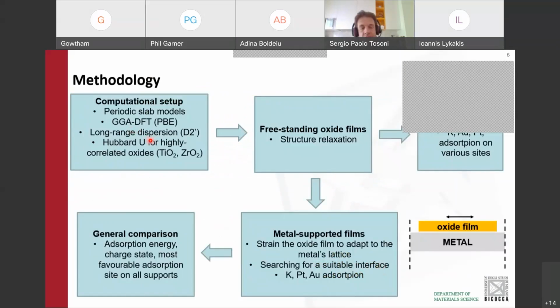The computational methodology that I adopted is the following. We are using periodic slab models. We treat the metal with generalized gradient approximation density functional theory, in particular with the PBE functional. We include long-range dispersion, and in those cases where the d electrons from the oxide display strong correlation, we use an oxide Hubbard parameter to correct.